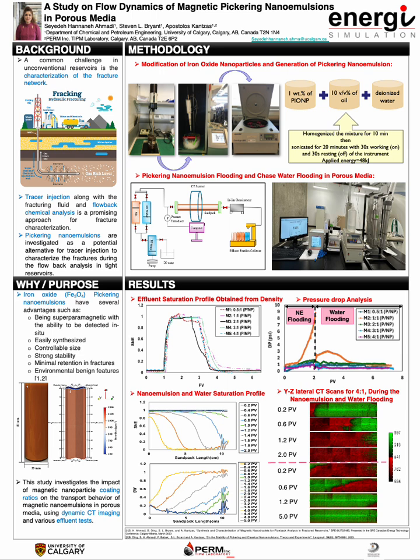To talk about the methodology that we used in this study, first we modify our nanoparticle by coating them with a polymer. In order to do that, we use a homogenizer, sonicator, and centrifuge to make different samples. The coating ratios that we use here were 0.5 to 1, 1 to 1, 2 to 1, 3 to 1, and 4 to 1, which is the ratio of polymer to nanoparticle, to investigate the effect of coating on the transportation behavior of nanoemulsion in porous media.